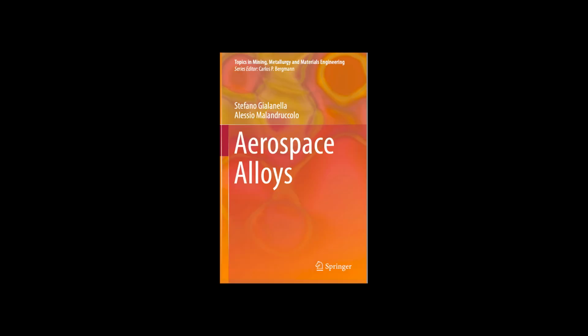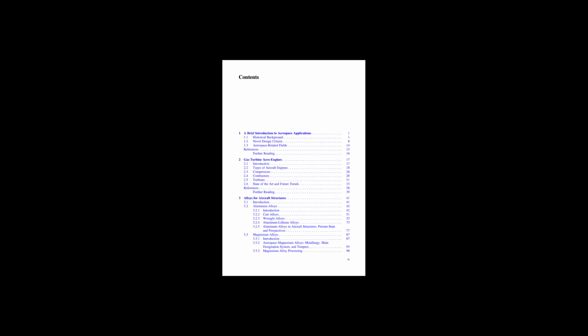One is hydrogen. Sometimes during rapid cooling with water, called quenching, tiny bubbles of hydrogen gas can get trapped inside the metal. It happens because the hot aluminum can react with water, producing hydrogen. If it can't escape, you get these little internal blisters. Not good. Another issue is impurities. If the aluminum isn't pure enough, you can get small, brittle particles of unwanted compounds forming. These act like weak spots, stress concentrators. They can make the material more prone to cracking. So purity is really key. Very key, especially for critical aerospace parts.